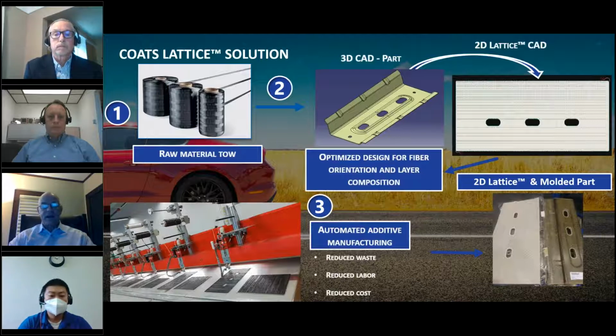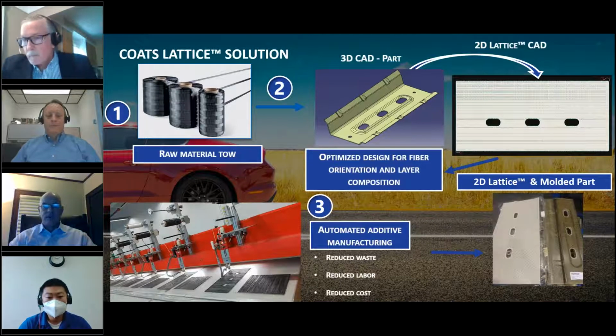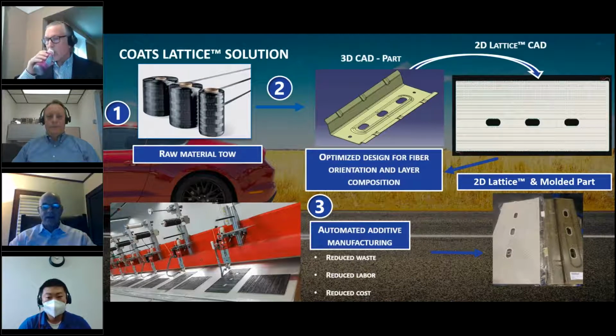The Lattice process is unique in that it allows us to fabricate near net shape continuous fiber preforms directly from either fiberglass roving or carbon fiber or both with no waste. We receive a 3D CAD model from the customer and use software to convert the 3D form into a flat two-dimensional pattern. We then program the customer's fiber orientations to develop the 2D Lattice preform. The preform is converted into machine language, and we use our multi-head TFP machines to fabricate the near net shape preform. Versus conventional technology, the Lattice preform costs less due to no waste and elimination of labor, and results in a higher quality and more reproducible preform.